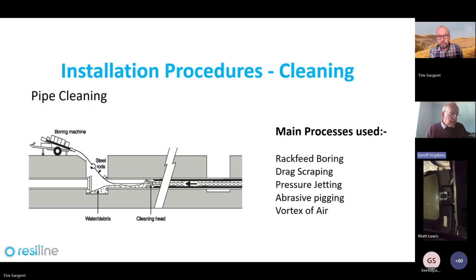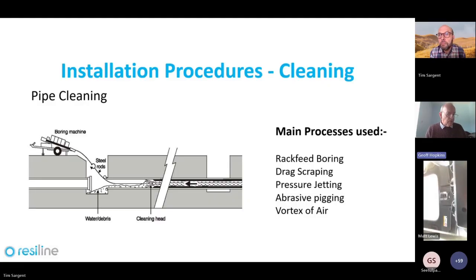Cleaning time is a function of the level of internal corrosion of the pipe and the diameter. But if the deposits inside the pipe are light, then a vortex of air machine could clean a pipe length of 100-120 meters in less than an hour. As I said, overseas it's mainly drag scraping or pressure jetting.